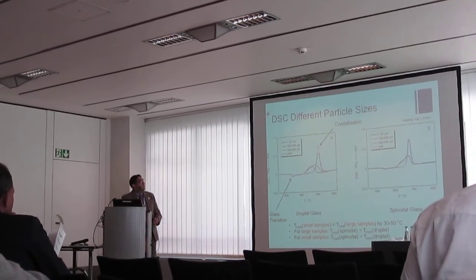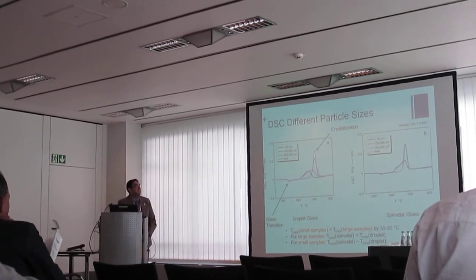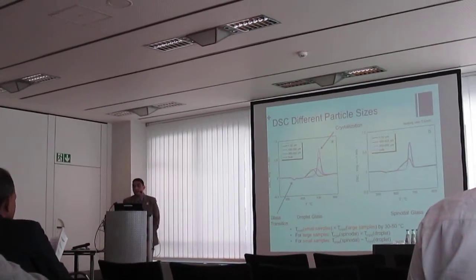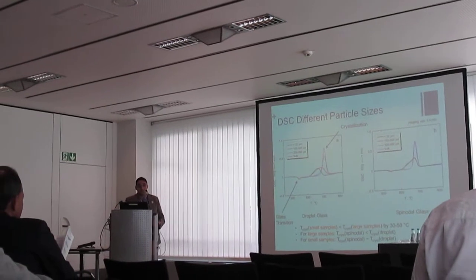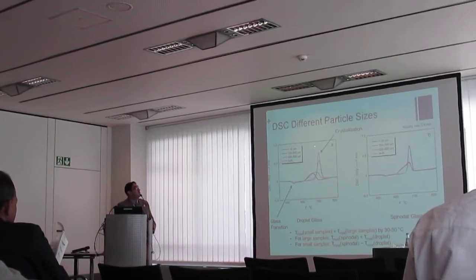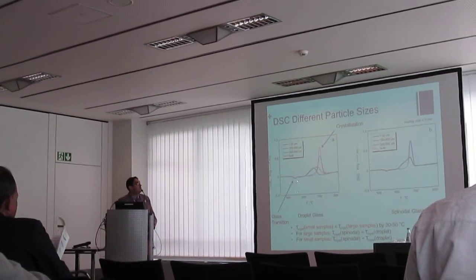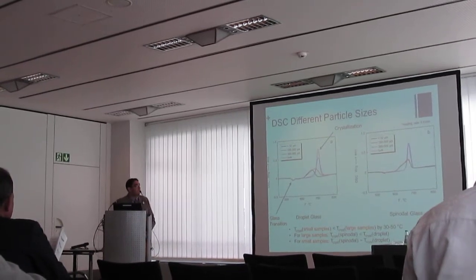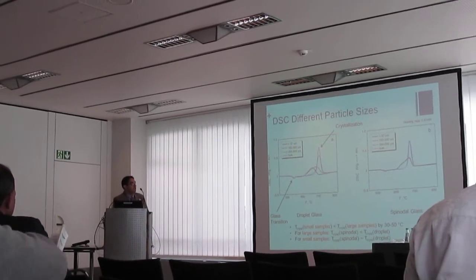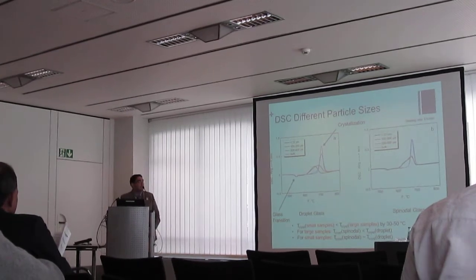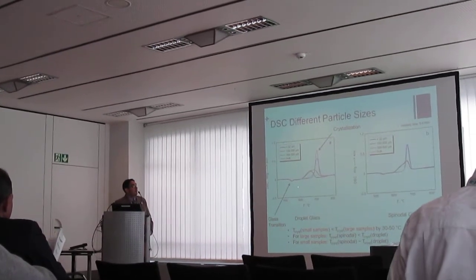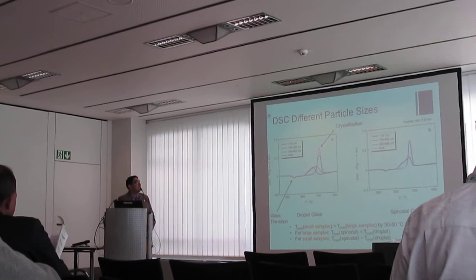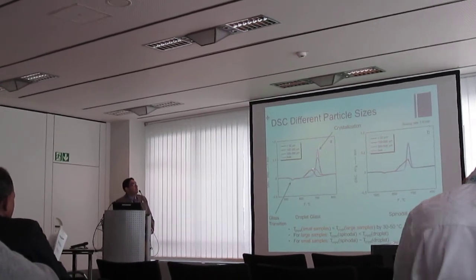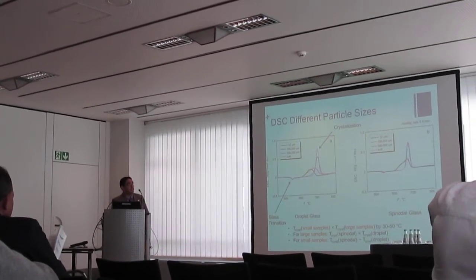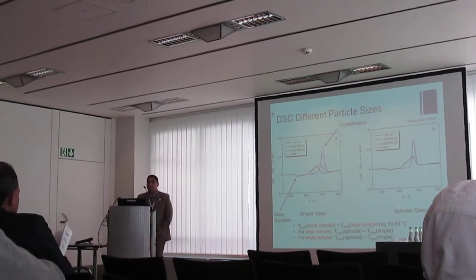This slide shows characteristic DSC curves for the two bioglasses we found. Just an overview of the DSC: we have two peaks here. The first peak, corresponding to about 550 degrees Celsius, shows the glass transition of the bioglass—both have the same glass transition. The second, exothermic peak shows the crystallization of the bioglass.